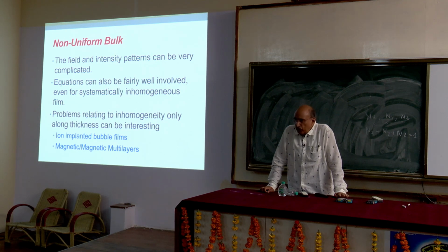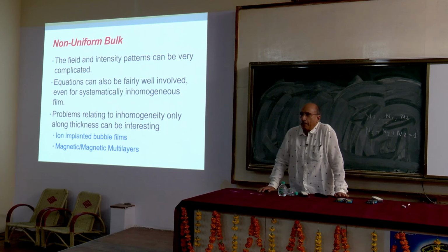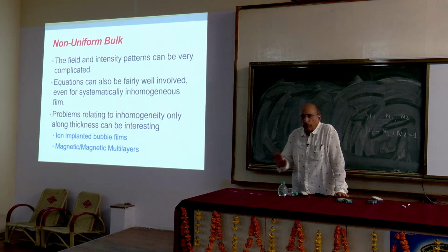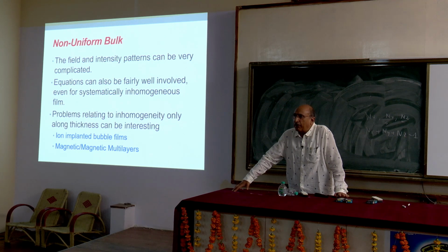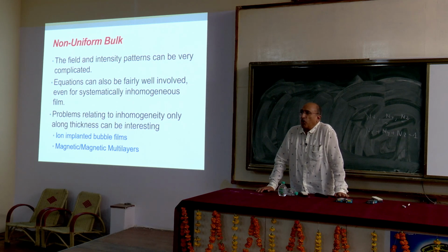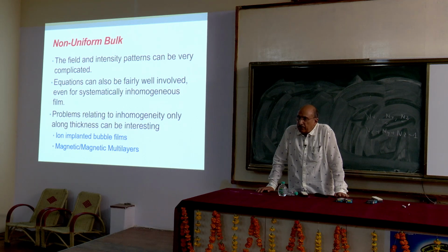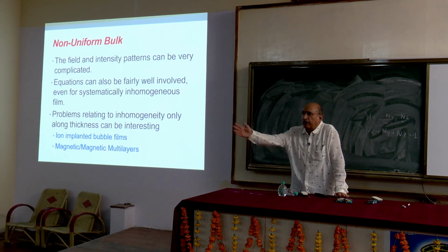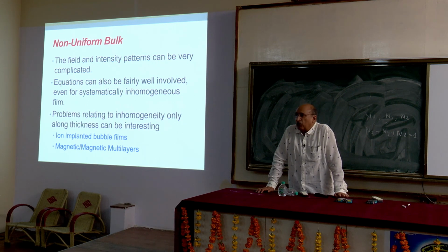See, how do you make bubbles move? You apply a magnetic field gradient, and under the force of that, bubbles will move. All the normal bubbles will move in one particular direction, which is along the gradient direction. But these hard bubbles will move at an angle, and they can go as much off as some degrees. If you have a few hard magnetic bubbles in your device, that will kill your device, because they will misbehave, and when you want them to be read, they will not be read. They will go elsewhere. So they were disastrous for devices, and people were finding a method to suppress these bubbles.